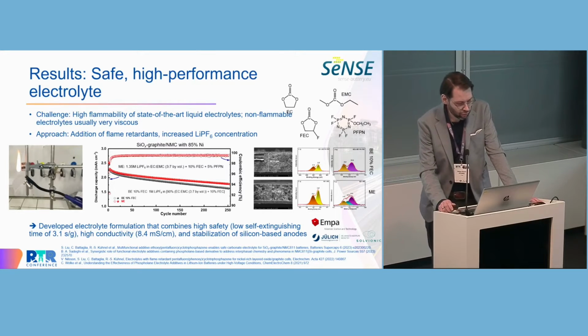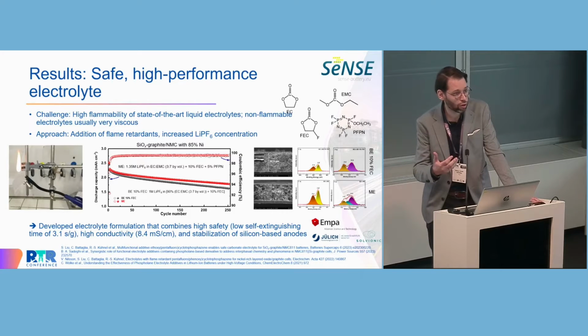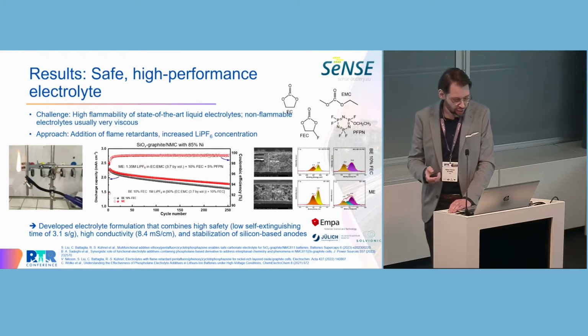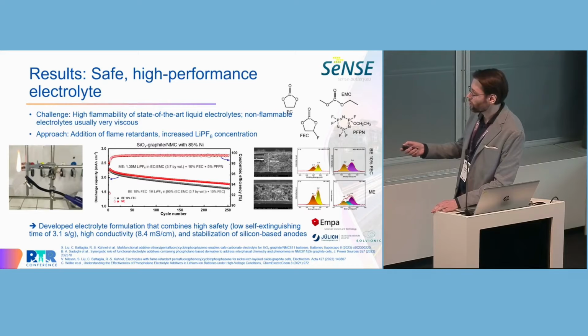What was then really nice for us to see is that this electrolyte retained a high conductivity of more than 90% compared to the baseline electrolyte, which was for us really important for the fast charging capability. And what we were then also pleased to see is that it also stabilized our full cells a bit. And we then investigated that in detail.